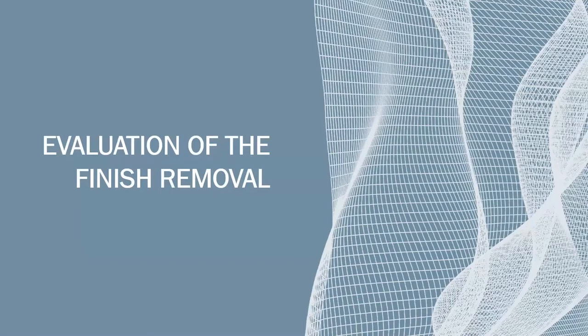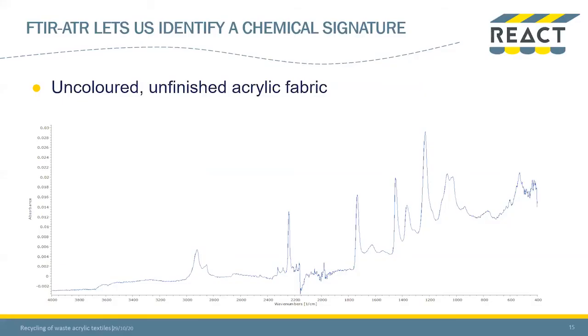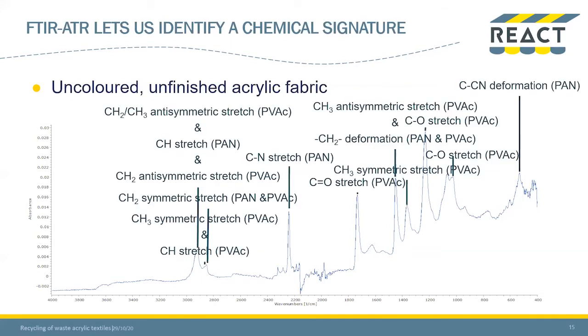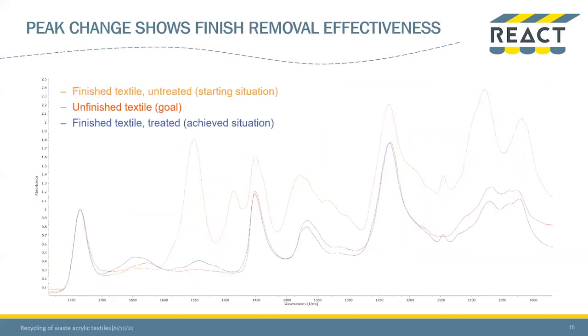So how do we evaluate this finish removal? Fourier transform infrared spectroscopy lets us identify the chemical signature of our fabrics and finishes, and an infrared spectrum of an uncolored unfinished acrylic fabric is shown here together with the characteristic peaks. The finish components have their own characteristic peaks. And if we follow the changes in their peaks, we can follow the finish removal efficiency.